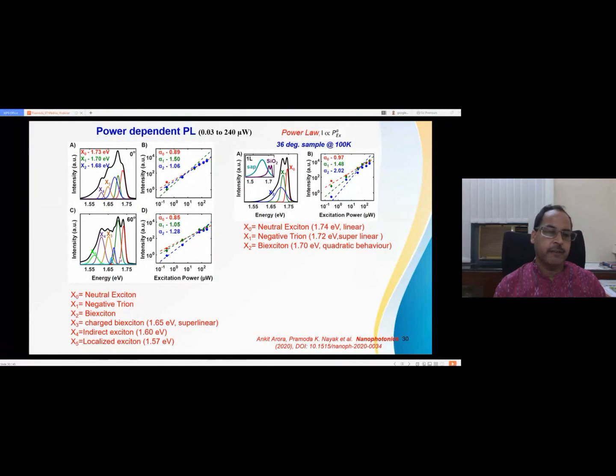Many peaks we find out, and because this is a comparison with the literature, to prove that these are this type of excitonic features, we have done the power-dependent spectrum by fitting the power law: the intensity of the PL is proportional to power to the power alpha. So using this alpha value, when it's close to 1, this is a neutral exciton.